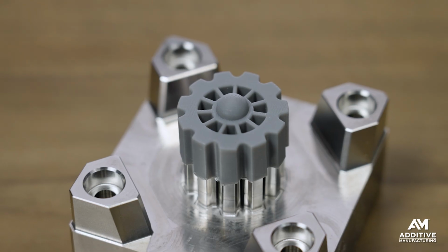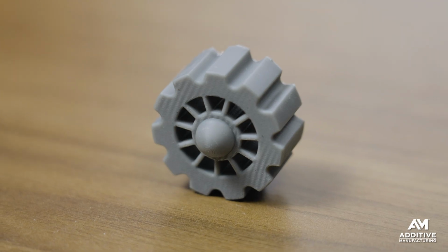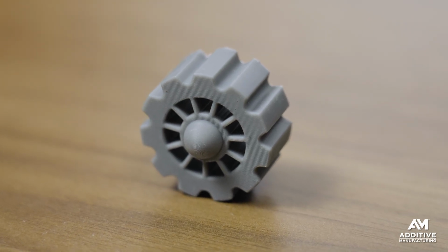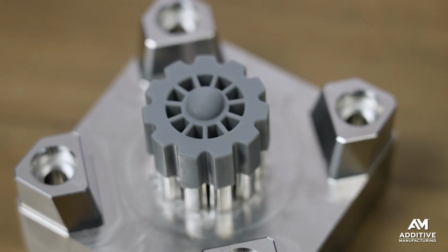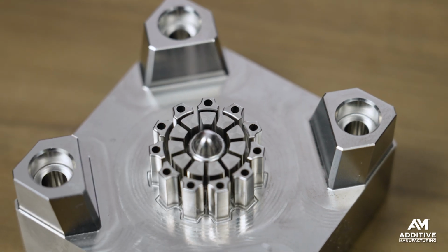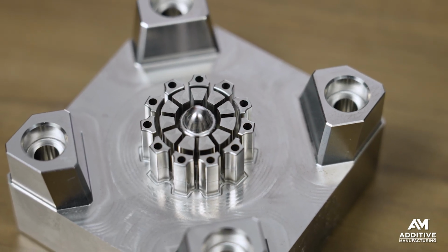This is the molded part. It is a precise control knob for a proprietary medical device. It controls flow rate or dosage. Molding this part presented a couple of challenges. One was the molding cycle time was taking too long, and that meant the injection molding capacity needed would be much higher than expected. Even more significant, oftentimes this part wouldn't mold at all because air would get trapped in the deepest recesses of the mold and the plastic wouldn't flow all the way in.